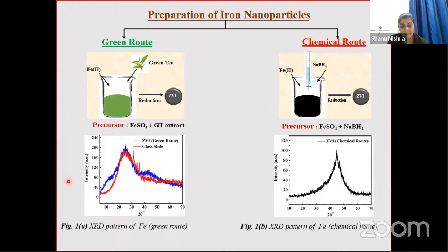In figures 1A and 1B, you can see the typical XRD pattern of both synthesized iron nanoparticles, which have a peak around 45 degrees, confirming the formation of zero valent iron nanoparticles. But in the case of the green route, you see a broader peak around 20 to 30, which denotes the amorphous nature of the synthesized iron nanoparticles. After this,